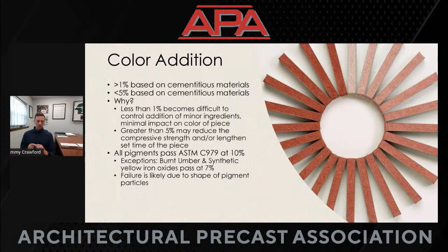Very difficult to achieve. Greater than 5%, you don't want to go too much over 5 for a variety of reasons. One being saturation point, but also over a 5% addition rate can have an effect on your compressive strength or increase the set time of a piece.